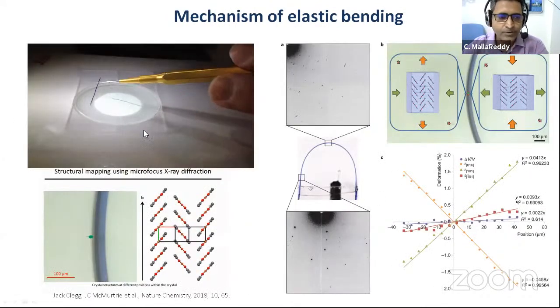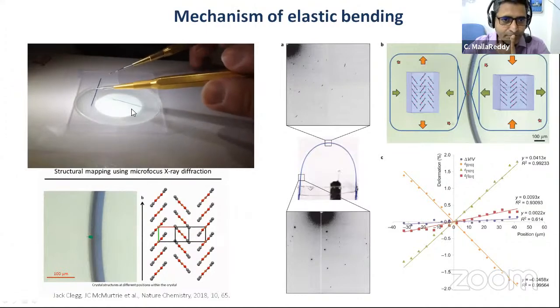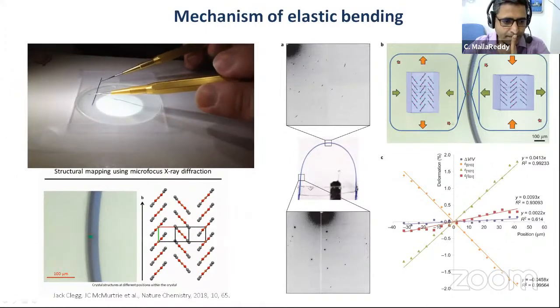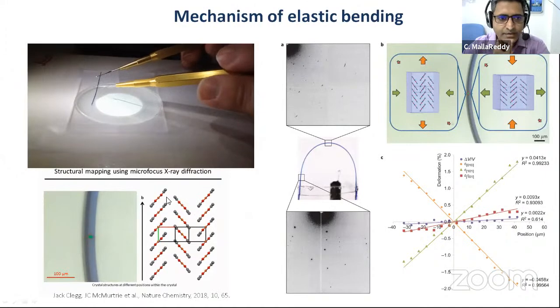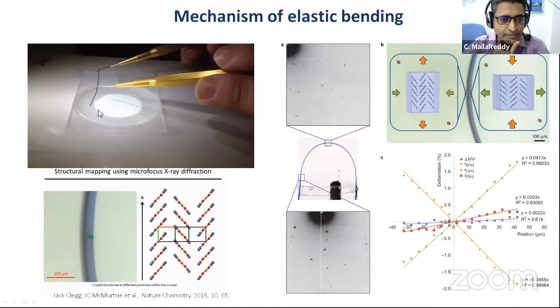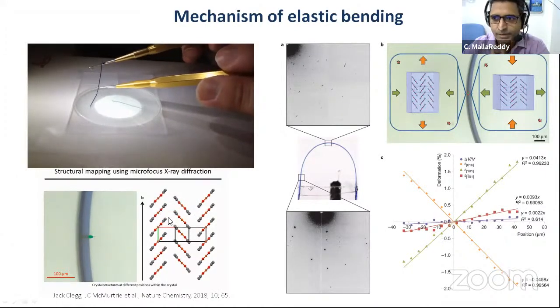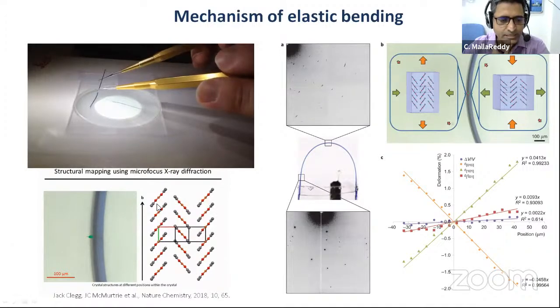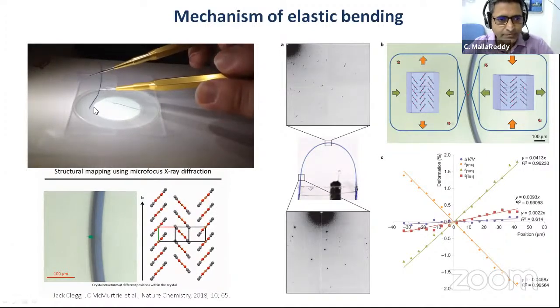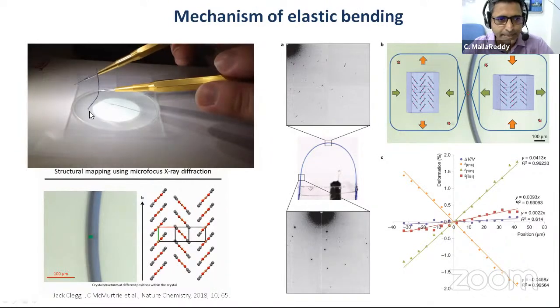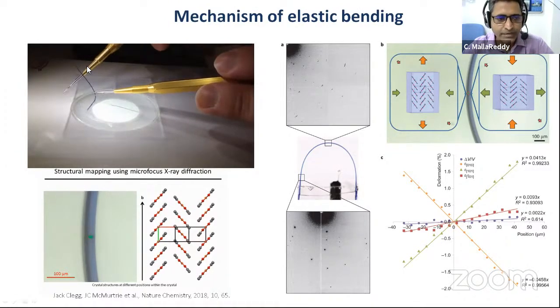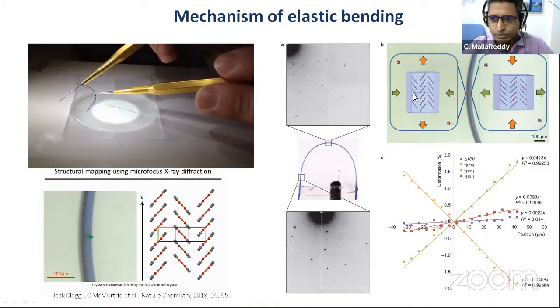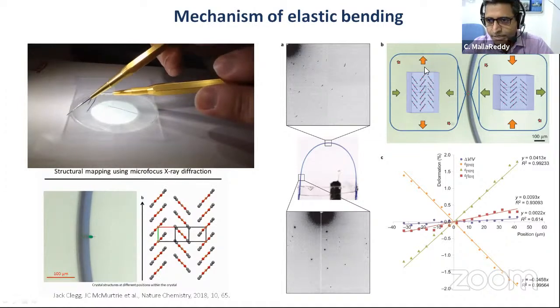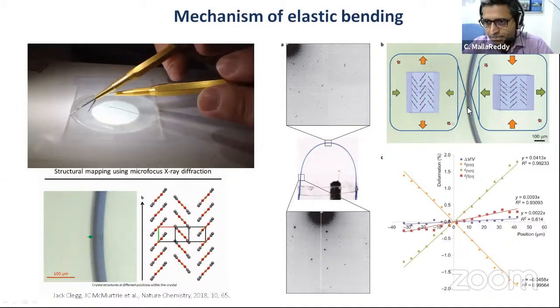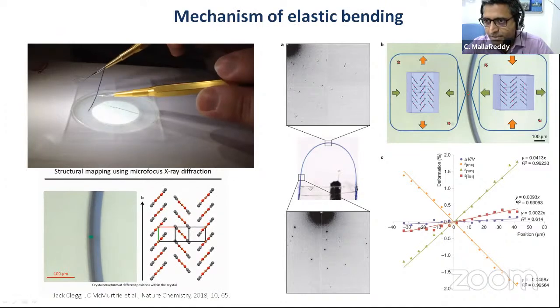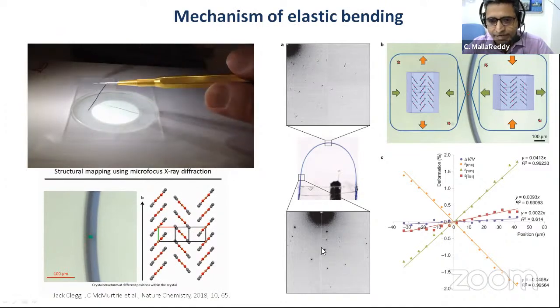So then when you come to the elastic bending, a group from Australia, Jack Clegg and McMurtrie, they have looked at this copper acac, so copper acetylacetonate crystals. So with these copper acac crystals, basically, if you take a crystal you can bend it and make a loop out of it. And so here, this is the packing. If you look along the needle direction, this is a bent crystal. They have done the diffraction studies here.